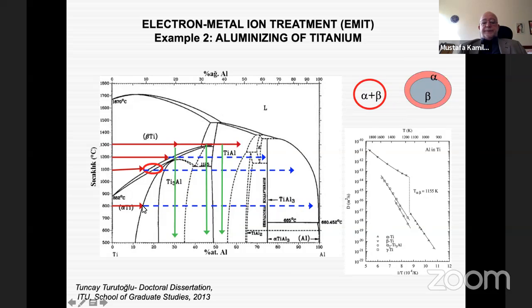When you reach here, the solubility, the diffusion of aluminum into titanium, dramatically decreases. Then you start to deposit metallic aluminum onto the surface, and your diffusion couple switches to the aluminum end. And as you see, there is very low solubility of titanium in aluminum. So we start to form the titanium aluminum 3 phase plus aluminum. That was what we were observing for the cases of 800 degrees and 1100 degrees. So here, the interesting story is this region. In this region, there is an alpha plus beta region. This narrow gap is composed of alpha plus beta titanium.